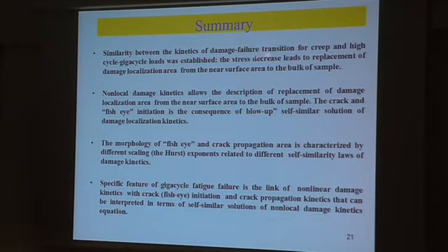Similarity between the kinetics of damage transition in creep and high gigacycle loads was established. The stress decrease leads to replacement of damage localization area from the near surface area to the bulk of the sample. Non-local damage kinetics, due to the nonlinearity of free energy release, allows the description of replacement of damage localization area from the near surface area to the bulk of the sample.